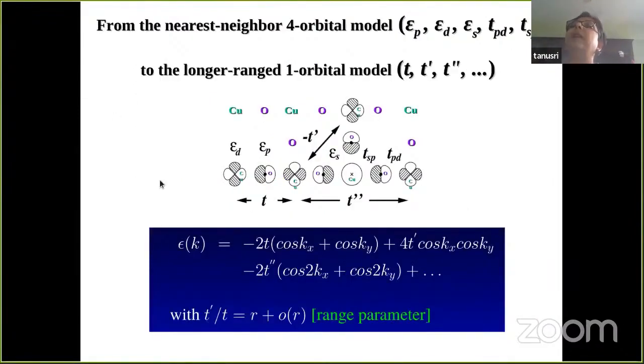So starting with such a model, which is basically a 4-band model, because you have the copper d, you have the oxygen px and py, and added to it you have the axial orbital. So it is a 4-band model, in contrast to the much discussed emery model, which was a 3-band model. But starting from such a 4-band model, you can actually derive a 1-band model, which describes the single band crossing the Fermi level in terms of the